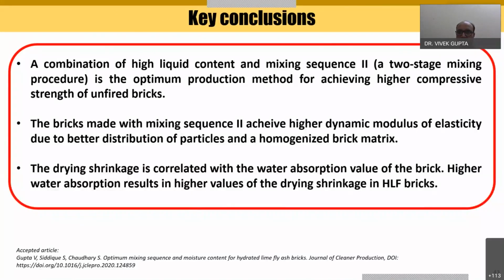These are the key conclusions from this particular objective, like the combination of high liquid content and mixing sequence two. Please note that the high liquid content should not bleed out, because if it bleeds out, then there may be chances of binder imbalance, and this may result in the deterioration of the performance. So the high liquid content and mixing sequence two should be in the workable range, and there we have reported an optimum production method for achieving the higher compressive strength of unfired bricks.